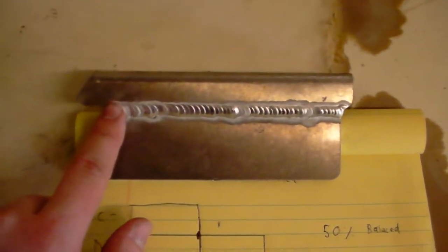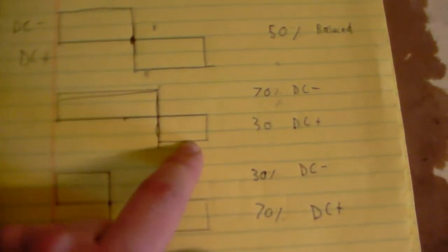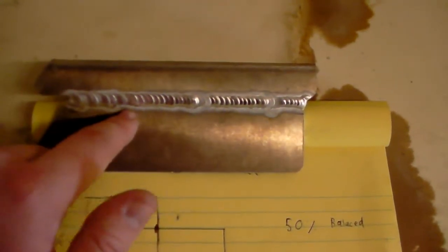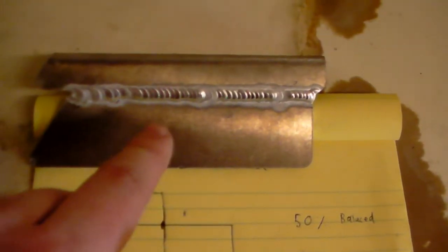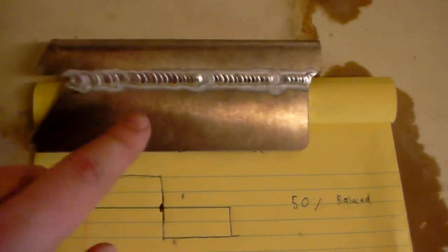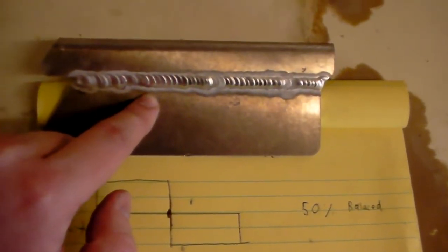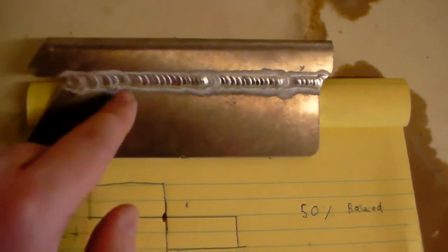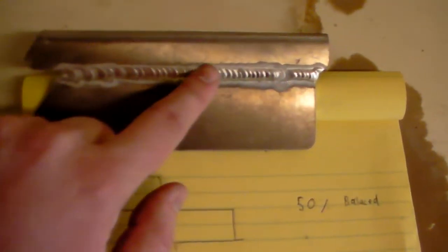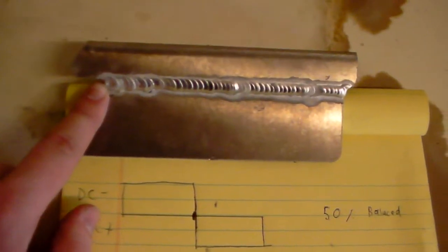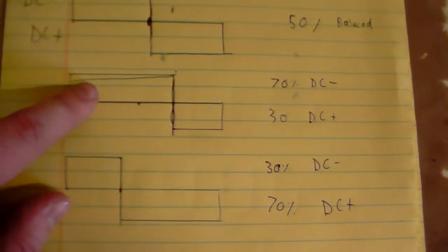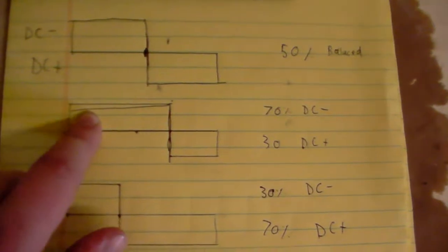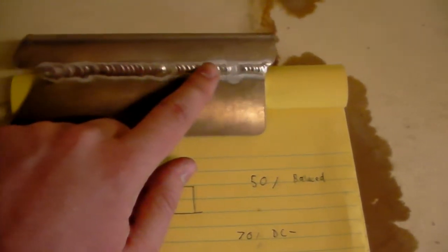it. So that's what the positive side of your AC arc is for. What this does is as the arc comes through the plate, jumps from the plate to the tungsten. Okay, remember, the positive side is from plate to electrode. So, from the aluminum to the electrode, as it makes that jump, it will blow the aluminum oxide layer out of the way. And then we can come in with the positive side, the heat side of our arc, and melt the aluminum underneath, which allows us to weld.